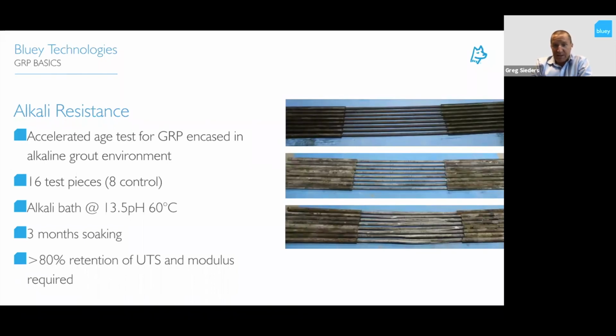Our bars on the marketplace, our GRP 60s, we get about 98% retention of the UTS and 100% retention of the modulus. Some bars that we've tested from different suppliers, and that we've seen test results on, can come back around 40 or 50% capacity or even lower. So this is why you've got to rely on individual tests for each product that's on the marketplace and not take one person's testing and apply that to every single bar.